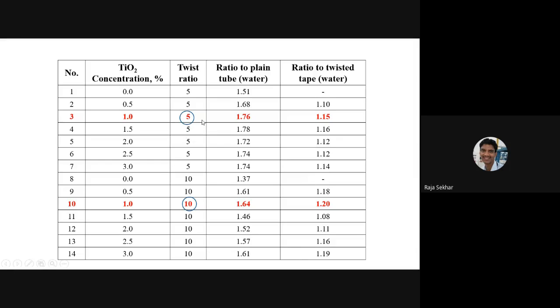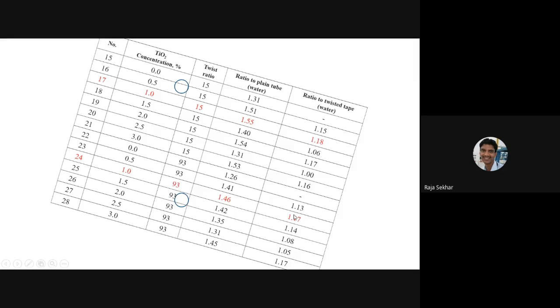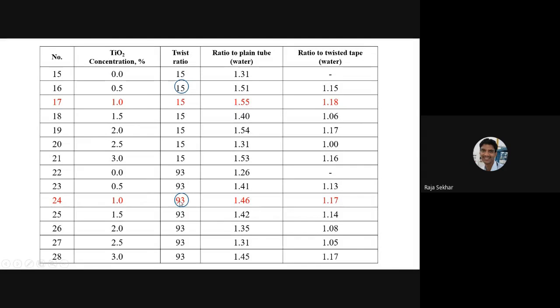This is for TiO2 with twisted tape. If you have a twist ratio of 5, at concentration 1 you are getting the highest. Similarly for twist ratio 10, at 1% concentration you are getting the highest enhancement ratios. For others it is lower. Similarly for 15 and 93, where 93 means almost a plain tape, at 1% concentration only you are getting it. I think in the earlier slide I have shown that for TiO2, 1% is the effective one.